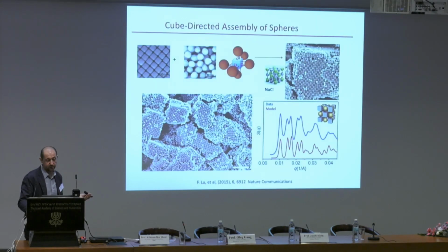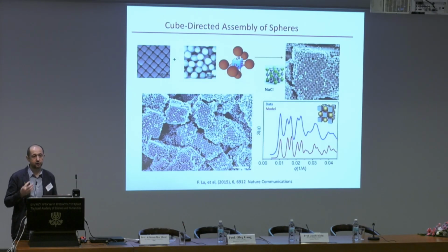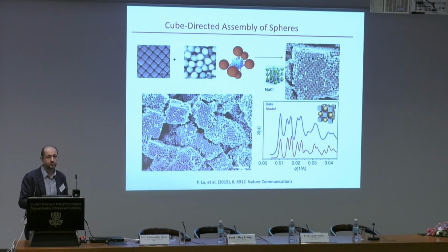So having this exploration in mind, indeed we could observe this co-crystallization of two non-complementary shapes, and from this point of view, you can also say that cubes essentially dictate how spheres will be organized. In this case, they're in six-fold symmetry, which is completely not native for them. It's a sodium chloride type of structure, where you have alternating order between cubes and spheres. We always rely on scattering for the really quantitative analysis, and that's also confirmed by scattering and modeling. So we have done something like this not only for cubes, but also using octahedra blocks, also of comparable sizes around 40 nanometers, made from gold. And we can also obtain crystallization driven by octahedra.